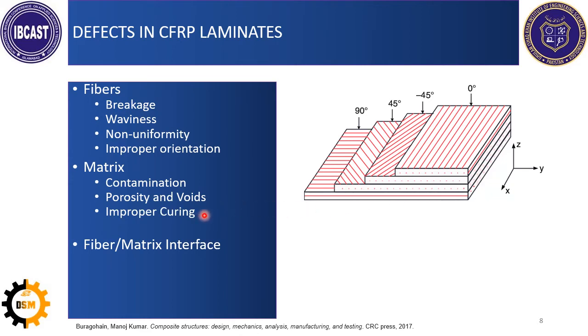The third one is improper curing. Every resin, epoxy resin, has its own thermal cycling, so you have to cure it accordingly. Some are cured at room temperature, some are cured in the oven, some are cured in a pressurized autoclave. So you have to follow those specifications. If you don't follow those specifications, the end product may have some humidity inside it, or it will not be properly cured, and when you put it under the real loadings, it may fail. So this is another problem in the matrix.